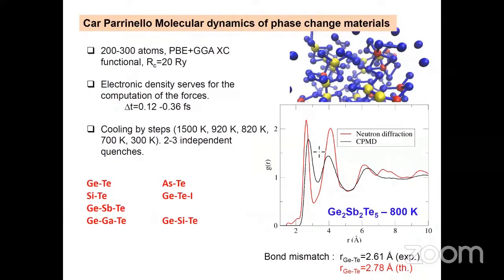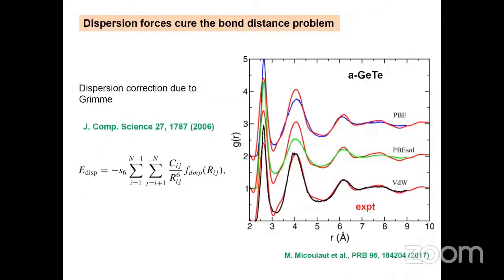That's the first point. And the second point is that there is obviously a bond mismatch in the first peak, which arises essentially from germanium-tellurium bond distances. And as you can see, the simulation is shifted to the right. So it is clearly overestimated: 2.78 for the theory, whereas it's 2.61 for the experiments. And so this tells us that, first, something is wrong.